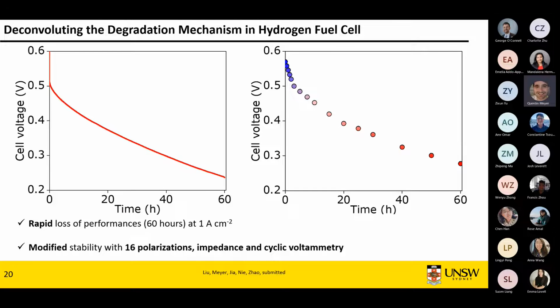So this is the stability performance of our catalyst in red. This, as I was saying, is actually a very respectable stability as far as PGM-free catalysts are concerned. It probably positions it in the top of the stability figure I was showing before, but basically in 60 hours you've lost half your performance. So what we've done is we've done some physical measurements at different steps.